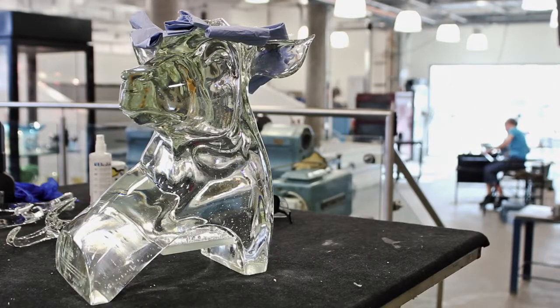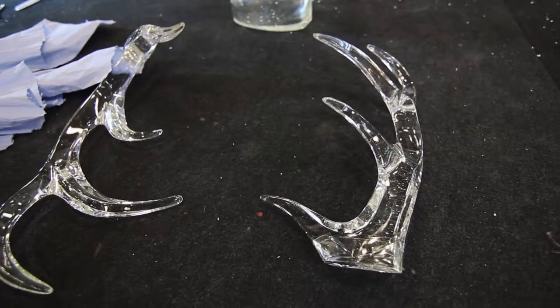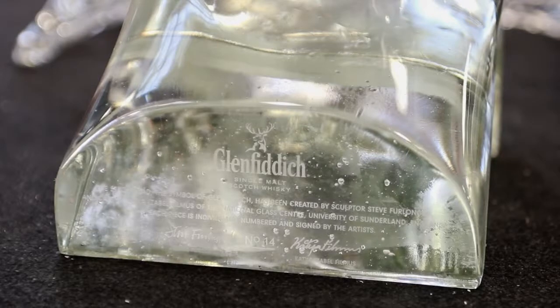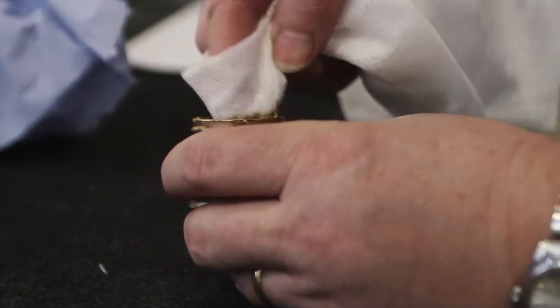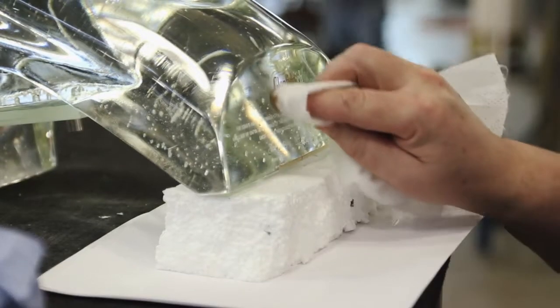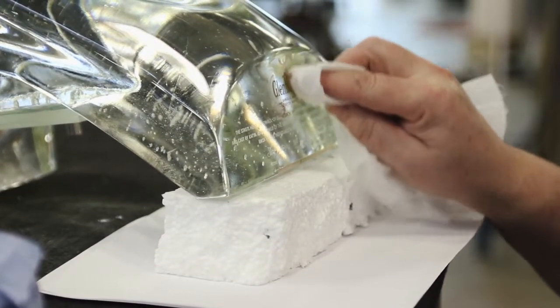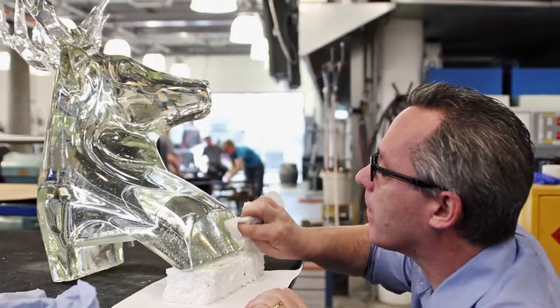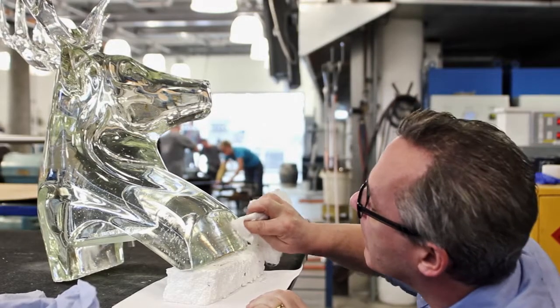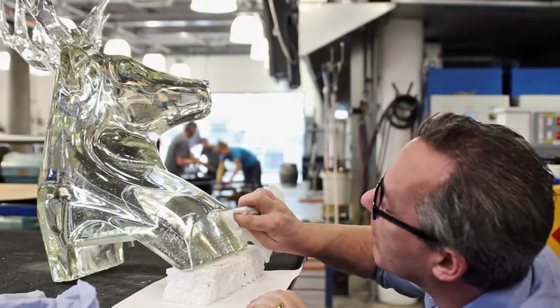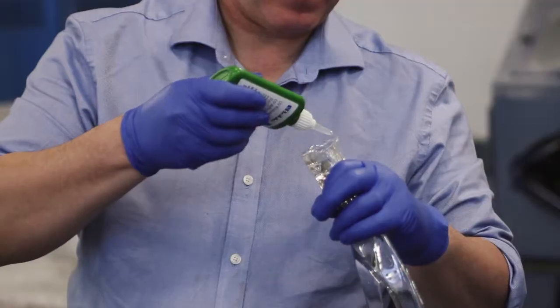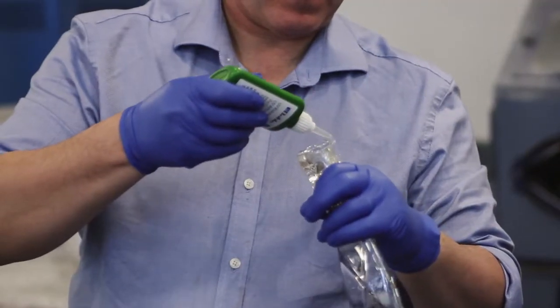So once we get the stag and the antlers back to the glass center, the first thing we do is to put it into a sandblasting chamber and sandblast the plaque that has my signature, the sculptor's signature, the National Glass Centre and the University of Sunderland logo, and of course Glenfiddich. They're all numbered, so each one of them has a number, and we UV bond the antlers.